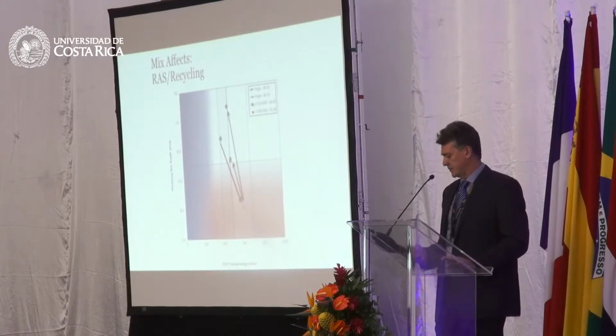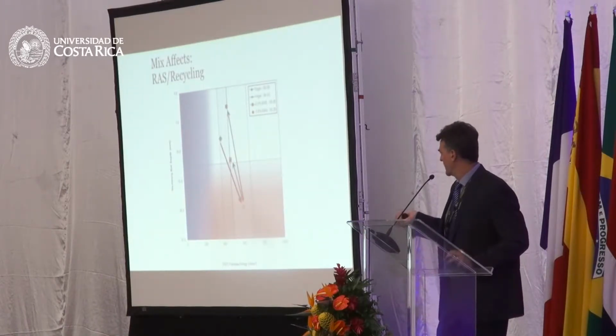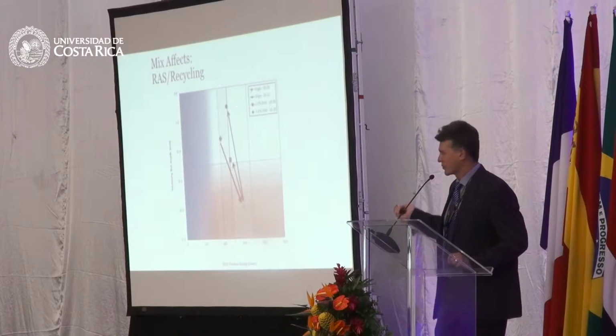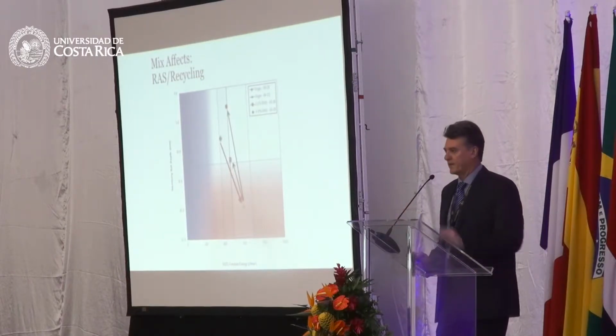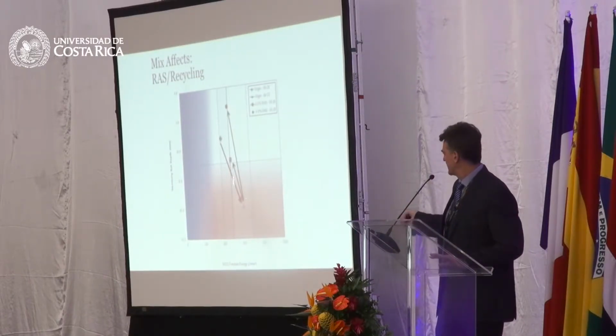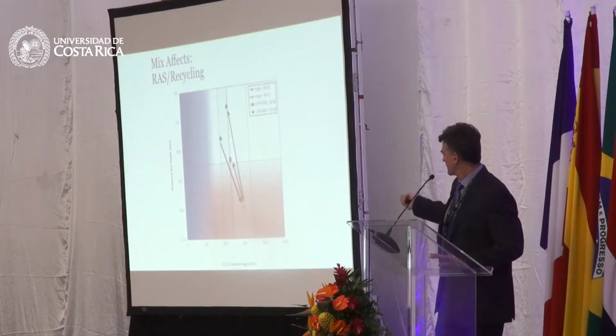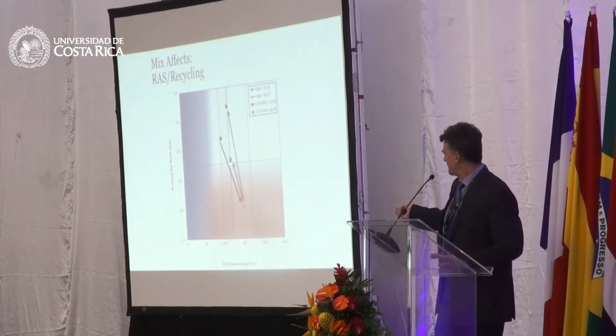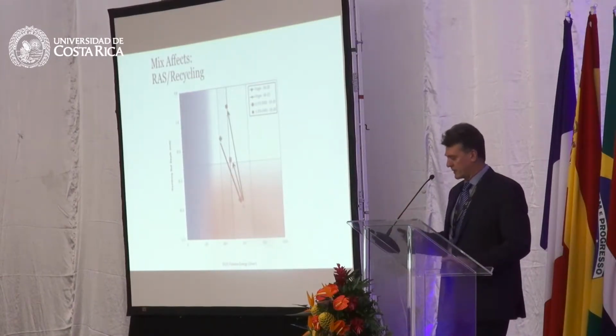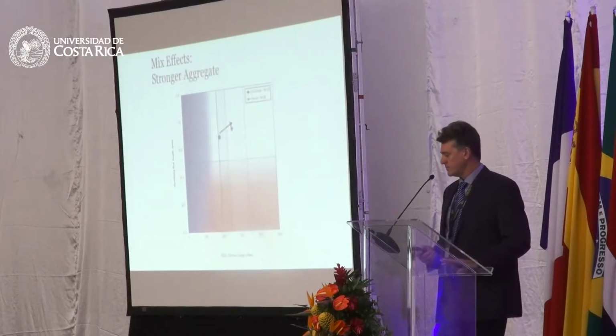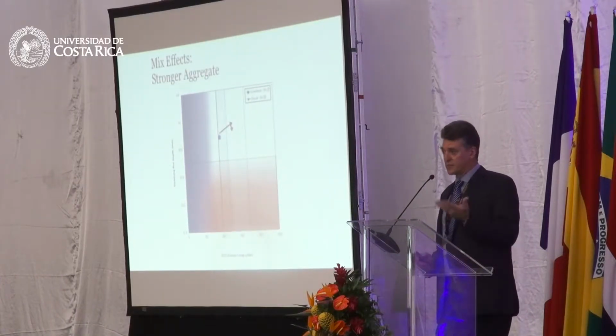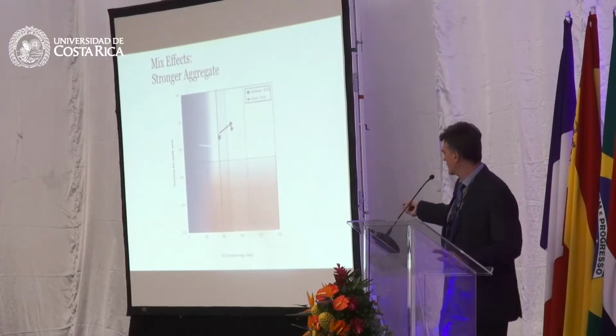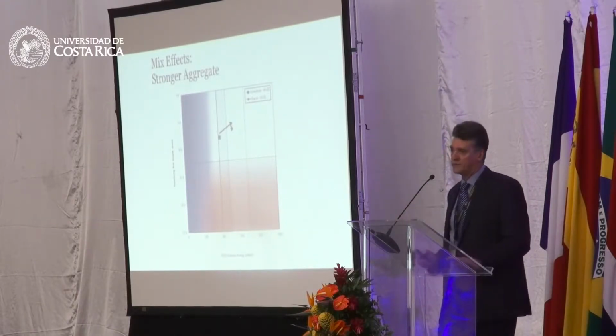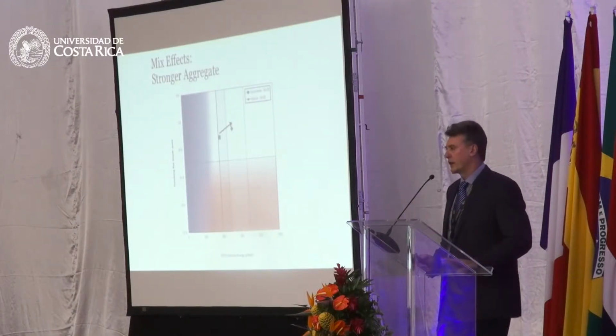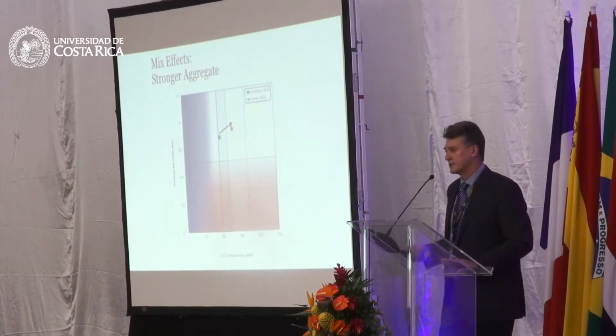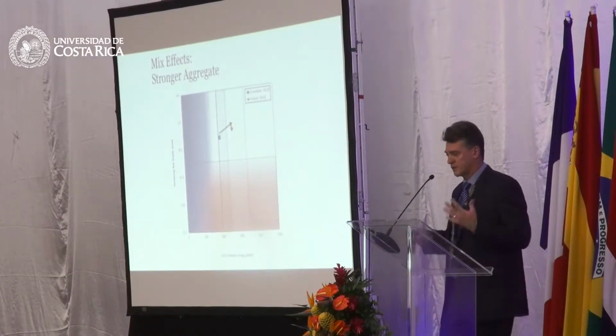You can also do it with other methods. This one illustrates when we use recycled roofing shingles. They have a slightly positive effect in pushing us more towards the corner here, but rather than just swapping the virgin binder grades, if you use a considerably stronger aggregate—we compared a weak limestone versus a strong gravel—it improved the rutting resistance and improved the cracking resistance of that mix, showing the investment in a better aggregate system.